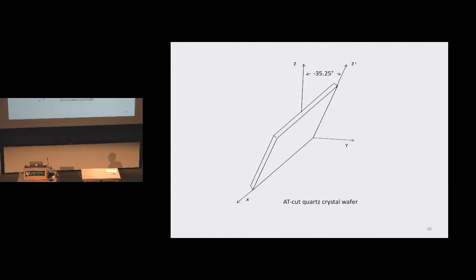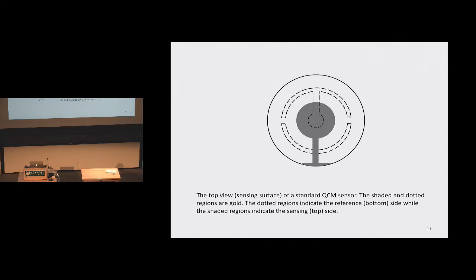All right, the common material that we use, AT-cut quartz. This is the X, Y, and Z coordinates in the crystallographic orientation, and this is the rotated, single rotated angle, minus 35.25 degrees. This material is very attractive. With electrodes on the top and bottom faces of this material, it will excite a perfect transverse shear mode with displacement components that are basically transverse to the direction of propagation, and further, that transverse shear mode is temperature compensated, which essentially means that its properties don't change as a function of temperature, and that is important in sensing.